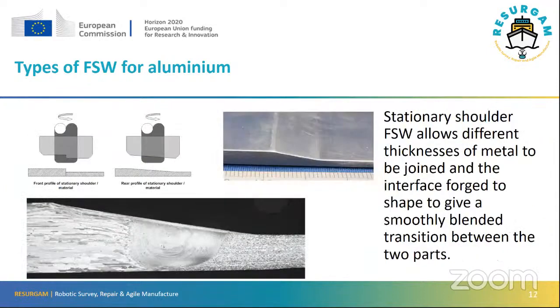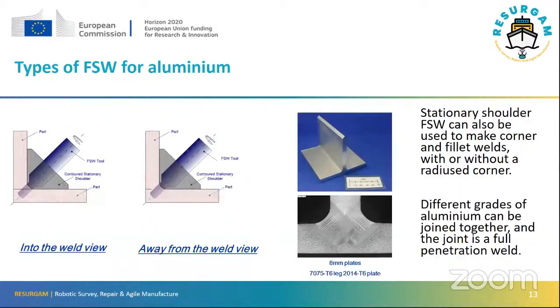We can weld different thicknesses of aluminium together by having a specially shaped tool, which then blends the joint line between the two plates and gives a nice smooth transition between the two parts. And in aluminium, we can also weld into corners and give a full penetrating joint. And under testing, we find that the failure tends to occur in the parent metal and not in the weld itself.